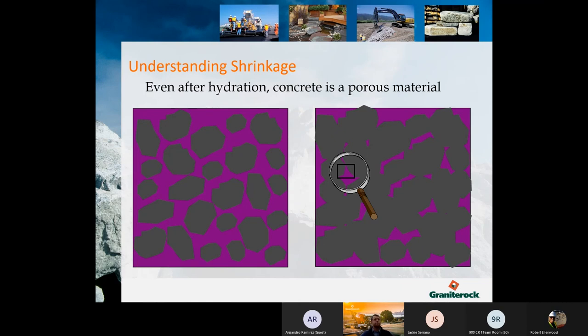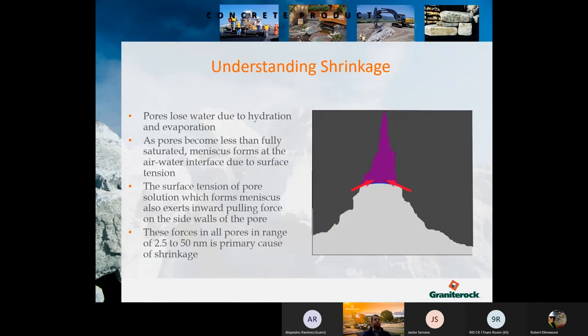So let's understand what shrinkage in concrete really is. Even after hydration, concrete's still a porous material. So there are capillaries, small tubes throughout the concrete, where when the concrete bleeds, it leaves an open void behind. Here's a close-up between aggregates. You can see how the moisture sits between there. When the pores lose water due to hydration and evaporation, and become less than fully saturated, the water between the rocks forms a meniscus, and it forms at the water-air interface due to surface tension.